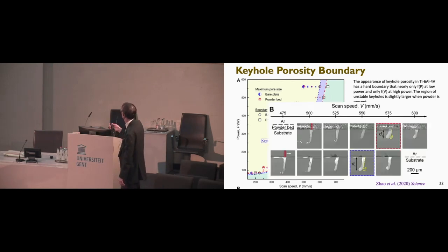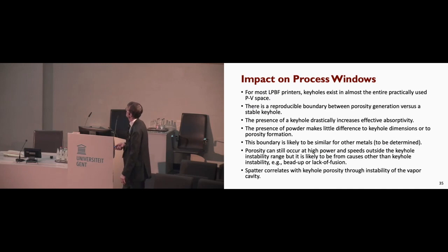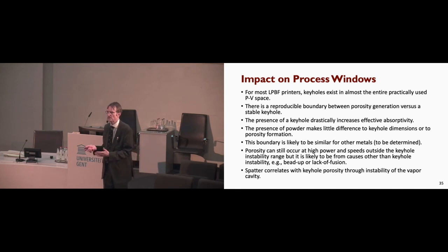And so you can go in and look at it in more detail. Here you see an unstable keyhole, an unstable one, a stable one, more or less. And that was with powder. Here you see unstable, unstable, but this one is more nearly stable, and so on as you go to higher speeds. So this was a good news story: by looking in great detail, we were able to establish that that boundary at least appears to be very well defined. And that turns out to be important because if you think that it should be possible to establish a process window for any given machine, then you have confidence that at least the boundary on one side is in a certain place, and it should not move around so long as you don't change your machine too much.